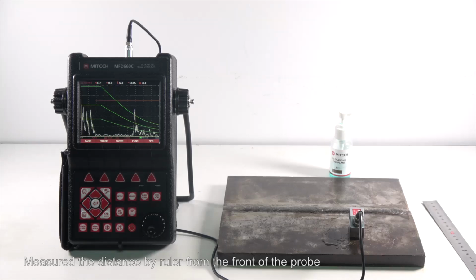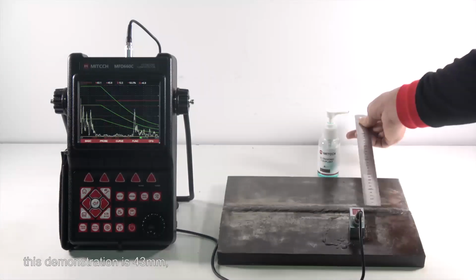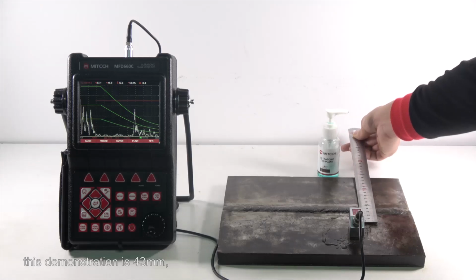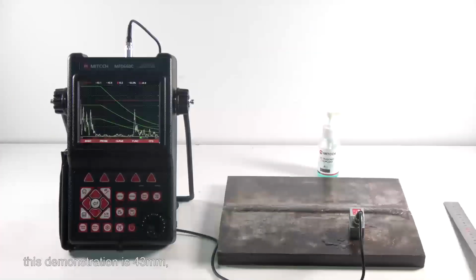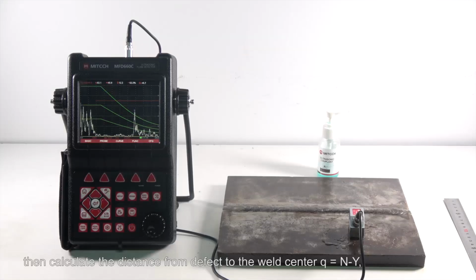Measure with a ruler the distance from the front of the probe to the middle of the weld, X millimeters, denoted as N. This demonstration is 43 mm. Then calculate the distance from the defect to the weld center: Q equals N minus Y, that is 43 minus 45.8, equal to minus 2.8. Fill in the form.